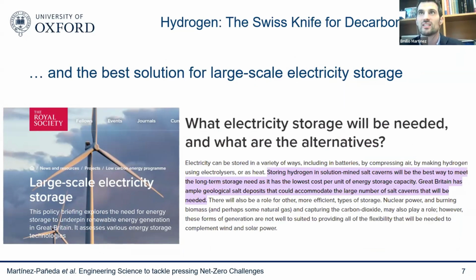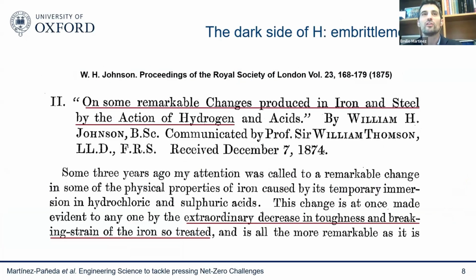So it's going to play a role, but at the same time, hydrogen has a dark side. We have known for almost 150 years that hydrogen makes metals very brittle. This was first reported in the Proceedings of the Royal Society, the oldest scientific journal in the world. It was reported by Johnson, as you can see here, where he speaks about some remarkable and extraordinary decrease in toughness and breaking strain in iron and steel in the presence of hydrogen. Scientists very rarely use words such as remarkable or extraordinary, particularly in those days, but the way that hydrogen interacts with metals is indeed quite remarkable and extraordinary.